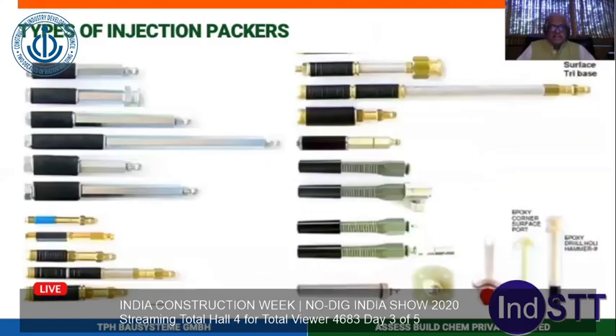viscosity. Another thing which is important is what offers the resistance to it, which is mostly the concrete. The surface tension is also important. Lower the surface tension, the more is the penetration. The less is the resistance, the less is the pressure required to push these materials inside.